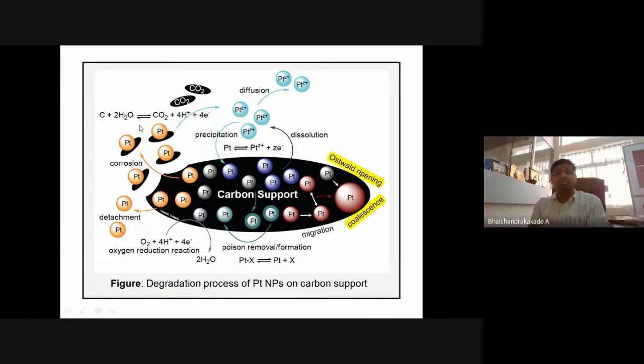At a potential much below, this CO2 is forming, which means this carbon support itself is not stable. If the carbon support is not stable, then platinum will also be dissolving out along with the carbon. Even if platinum remains stable, carbon itself is going out, so carbon leaches out, platinum also will go, so it will cost more. So what is the problem? Carbon dissolution is one problem. Second one, the oxidation of the platinum. This oxidation means corrosion of the platinum takes place because of the formation of some ionic sites, or permanent bonds will form with carbon monoxide, or some hydroxyl species will form. Those platinum are of no use.